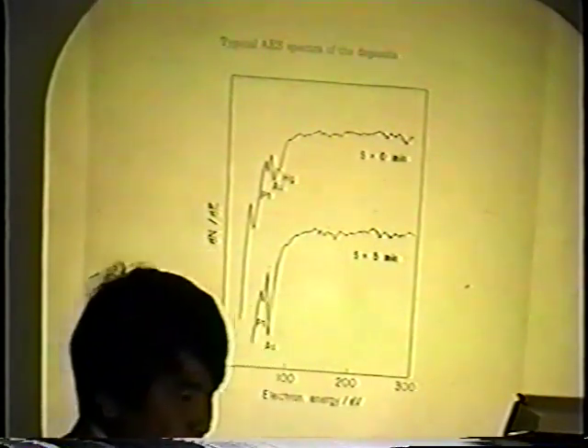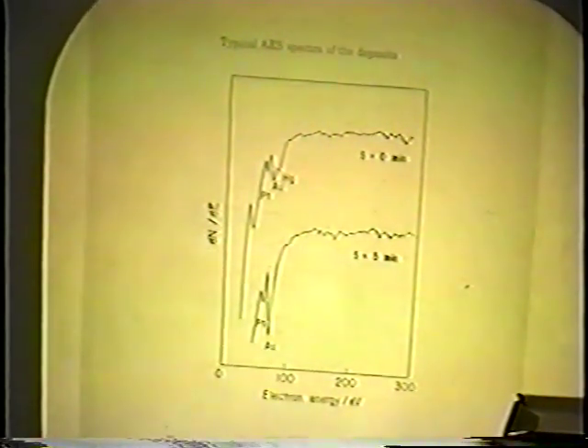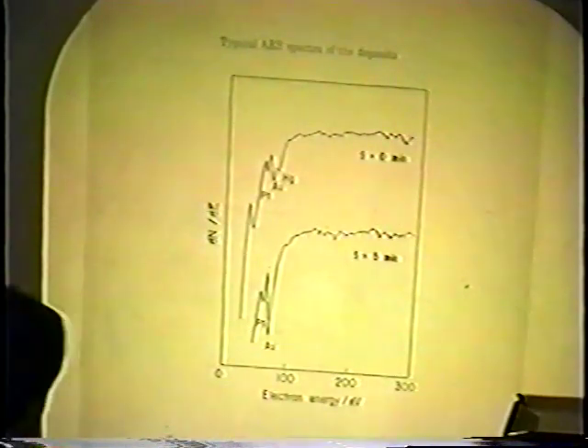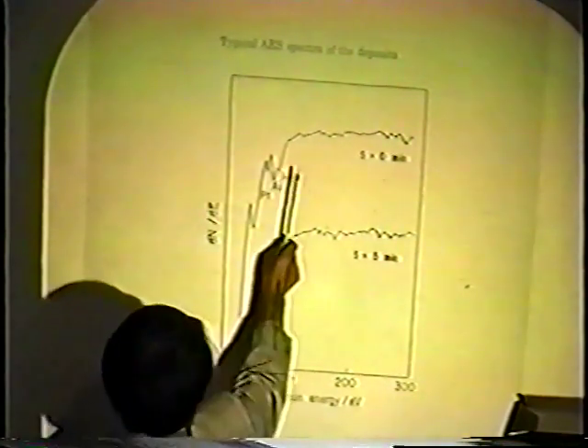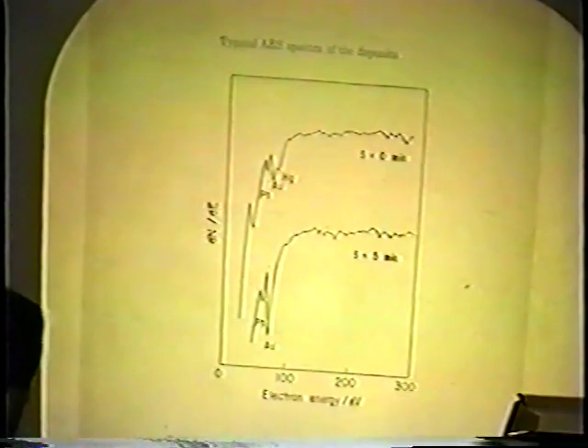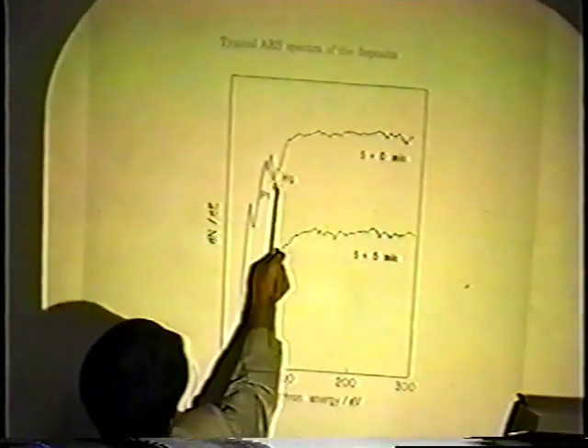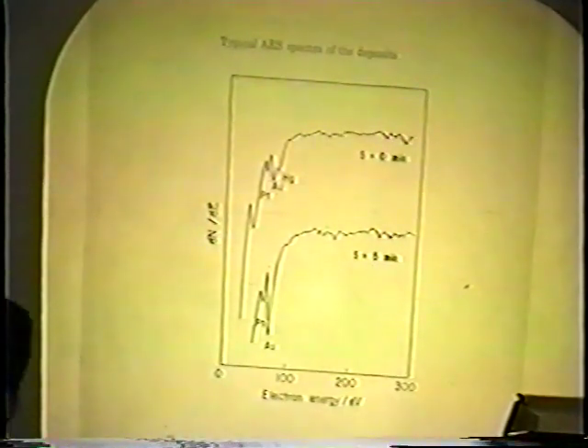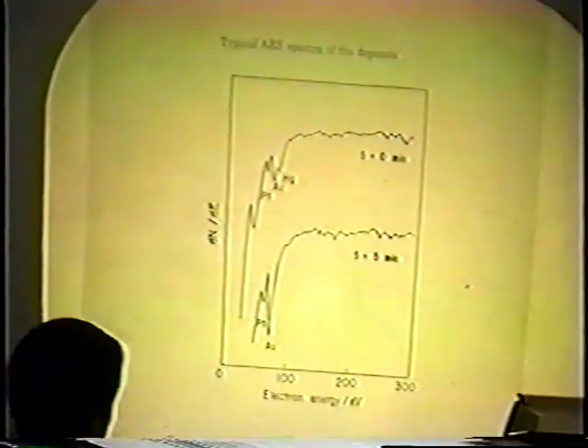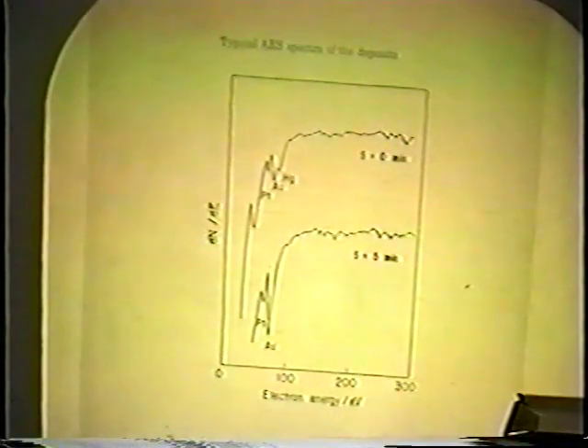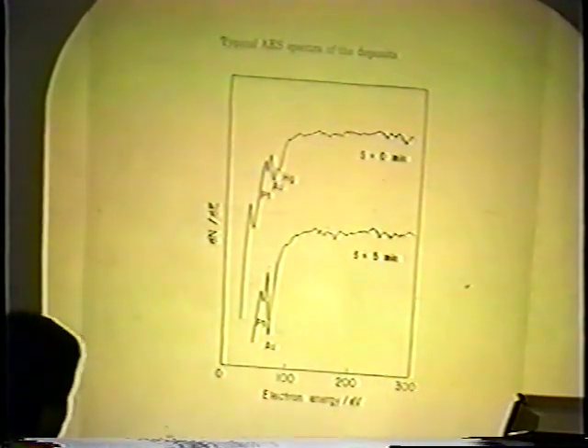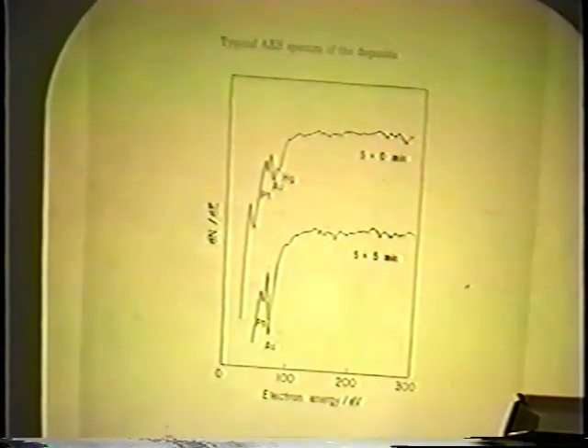A typical AES spectrum of the deposit is shown in this figure. As seen from this figure, a mercury signal is observed together with gold and platinum signals. After sputtering for about 5 minutes, the mercury signal disappears. However, in some cases, the mercury signal remains even after 10 minutes of sputtering.